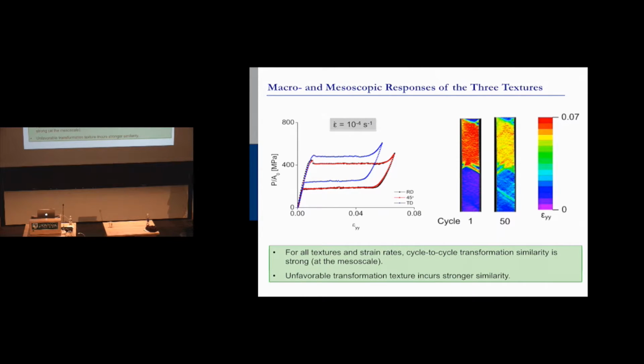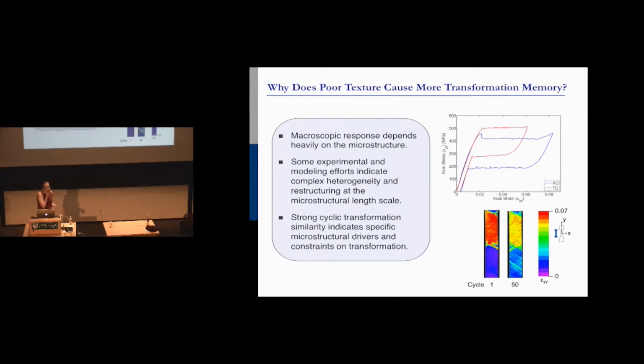But why would that happen? What is it about the grain structure that having a worse transformation characteristic actually makes it better in terms of cycle to cycle predictability? And so we said, well, we really want to look at this. Why does poor texture cause more transformation memory? What is it about that? Some of the things that we knew: the macroscopic response depends heavily on the microstructure. That's known. So here, remember this is the RD, this is the TD. You change the microstructure, you drastically change the performance of this material.